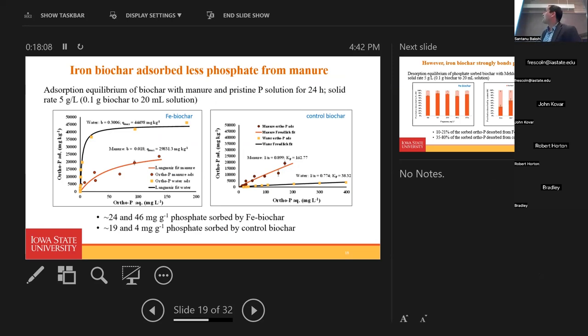In this slide, I'm showing that iron biochar adsorbed less phosphate from manure. We did the adsorption equilibrium with biochar and manure for 24 hours, with a solid biochar addition rate of 5 gram per liter. On the left-hand side, I'm showing the iron biochar, with the model fitted with the Langmuir isotherm. On the right-hand side, I'm showing the control biochar, with the model fitted with the Freundlich isotherm. Please note that iron biochar is nicely following the Langmuir, but the control biochar is following just the Freundlich. Langmuir is monolayer specific adsorption on the iron hydroxide surface.